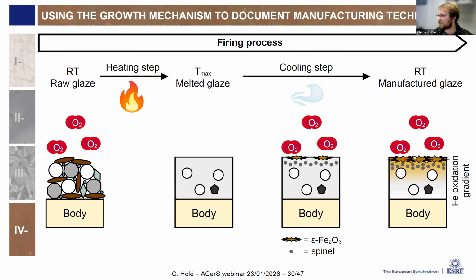And the bigger the iron epsilon oxide grows, the deeper the spinel should go, because we need to pump new divalent ions from deeper inside the glaze to continue this mechanism. And actually, these gradients might hide an interesting key for documenting the manufacturing techniques and the firing processes, being in a way a fingerprint of the techniques that were used to fire, the conditions in which the ceramics were fired.